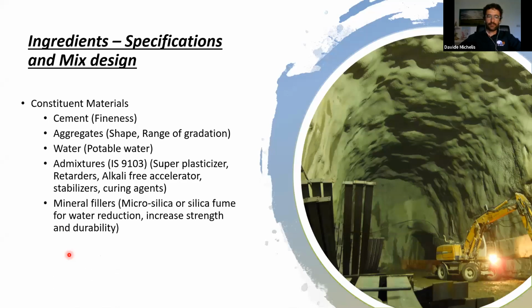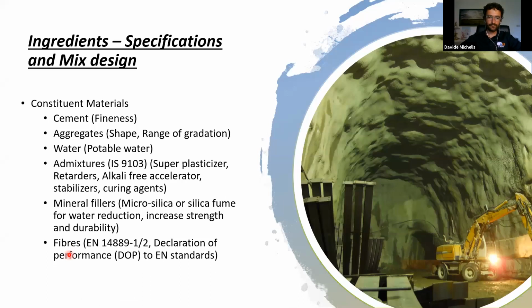We can also add, and sometimes it is absolutely mandatory to use, mineral fillers like silica fume, microsilica, in order to reduce the water amount and increase final strength and durability of the final product that we are applying on the surface. Fibers, as introduced before, can be both steel, plastic, and we will see later which ones. And this is an additional product that is enhancing the flexural strength of the product.